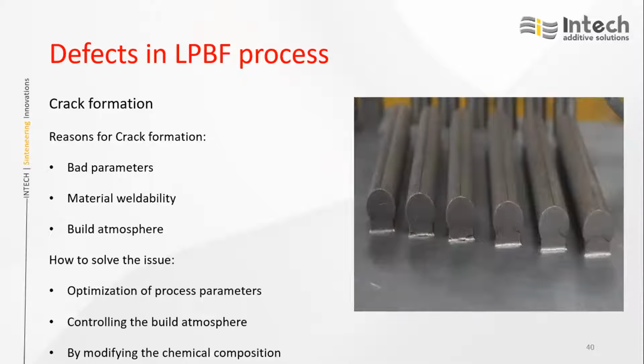And in this slide is crack formation. This is because the material may also be prone to cracking sometimes. In those cases, we need to optimize the process parameters properly, and we need to check material weldability. Only weldable materials are processed by additive manufacturing. And the atmosphere we are using, the chamber, needs to be checked. How to solve the issue is we need to optimize the process parameters, control the build atmosphere, and if the material itself is prone to cracking, then we may need to modify the chemical composition without affecting the final properties.